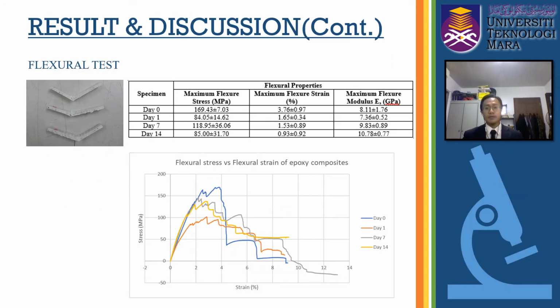Four specimens were prepared for testing using the flexural machine. The specimens that were tested were submerged in distilled water for 0 day, 1 day, 7 days, and 14 days. This test was conducted to know the capability and strength of each specimen and to find out which one is a good product when submerged for a certain time.